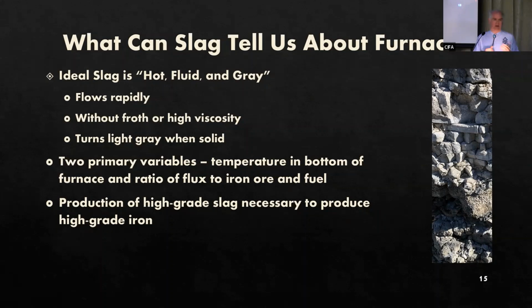Gray slag generally indicated that the iron produced in the furnace was high grade and contained a little bit of carbon in the form of graphite. Darker gray and black slag, on the other hand, suggested that the iron was lower grade and contained less graphite carbon.